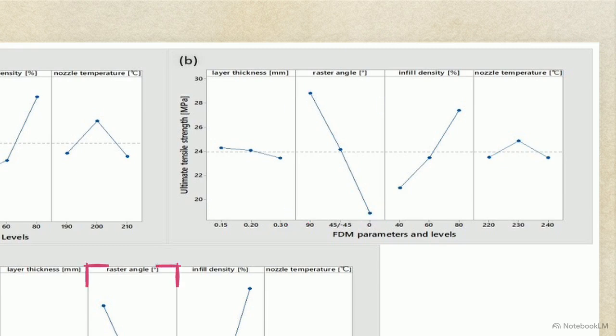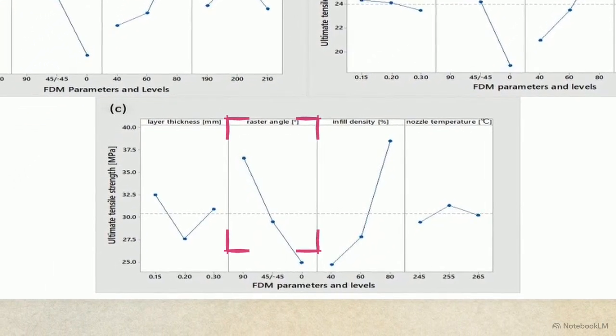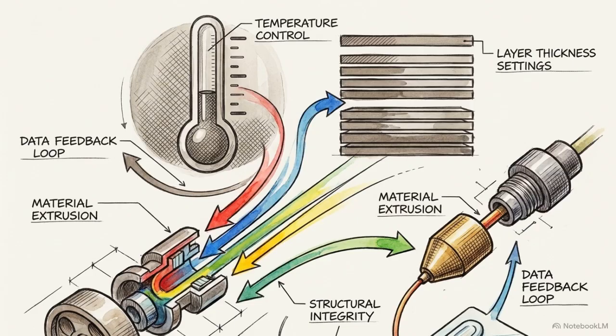The raster angle, the direction the nozzle travels while filling the interior, dictates the part's capacity to resist tension. Across all 3 polymers, a 90-degree raster angle provides the absolute optimal orientation for maximizing tensile strength. The performance gap is massive. Orienting the toolpath to 90 degrees outperforms a 0-degree angle by 47% to 52%, depending on the plastic. In stark contrast, parameters like layer thickness and nozzle temperature barely register an impact on ultimate tensile strength in these tests. The physics behind this are straightforward.